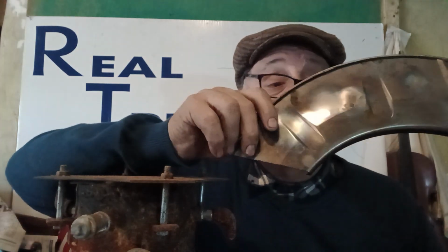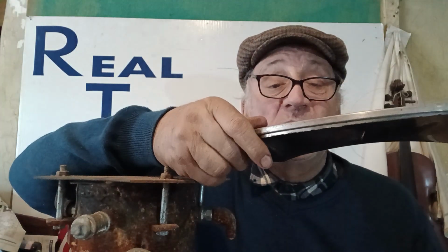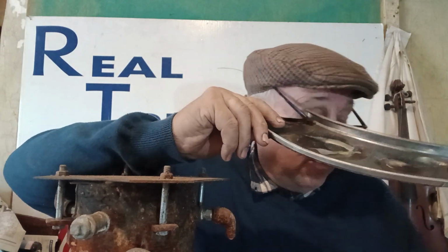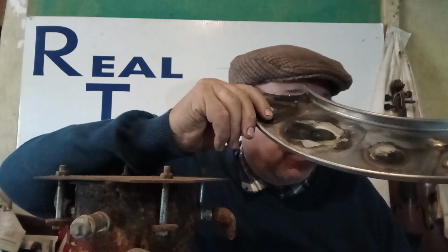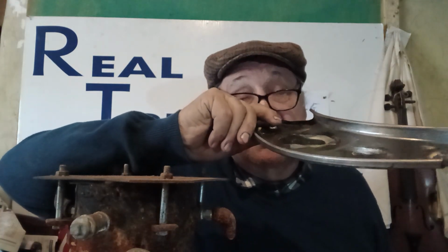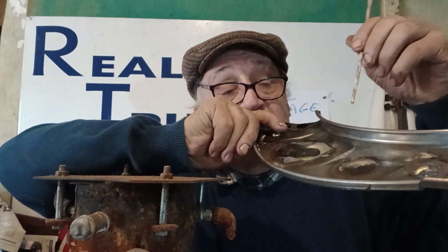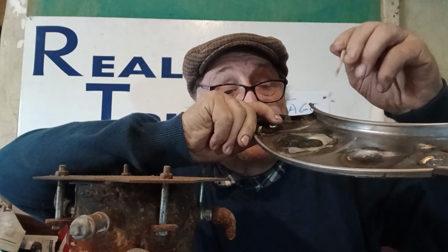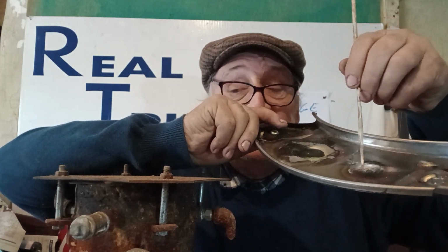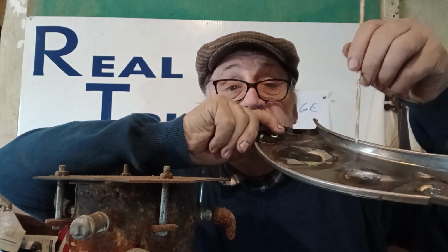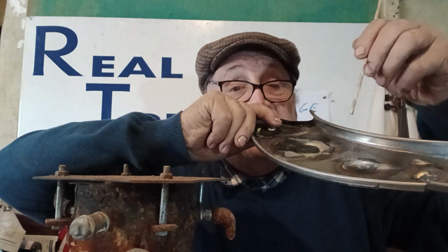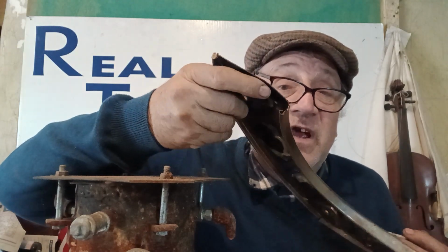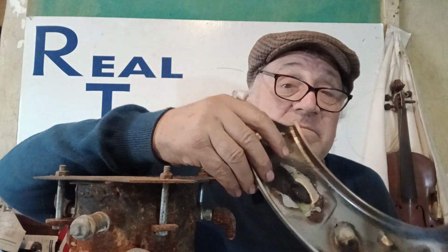So this is stainless steel, and the problem is when you put the gas on this, it gets too hot, and you can't get your brass rod, or bronze or brass, up to the temperature. By the time you get this hot, this is mad hot, and it's beginning nearly to melt. It's hard to get this to do it. So the problem is that this is too thin in section. Do you see? It's too thin.